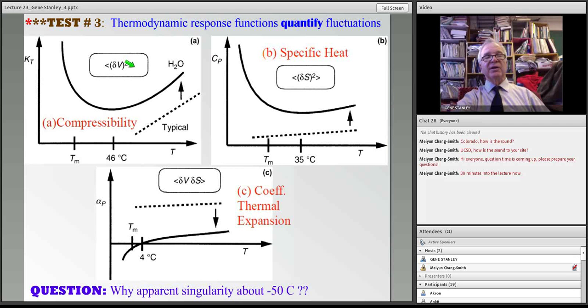And we see here that same, this is a schematic of the data I just showed you with a minimum at 46, and that the fact that the compressibility starts to increase means that the volume fluctuations are actually no more decreasing, as our intuition would tell us, and as is true for typical liquid, but they actually start to increase. Similarly for specific heat, the specific heat corresponds to the entropy fluctuations, and the entropy fluctuations, as in almost all liquids, decrease as you lower the temperature, but below 35 Celsius, they start to increase.